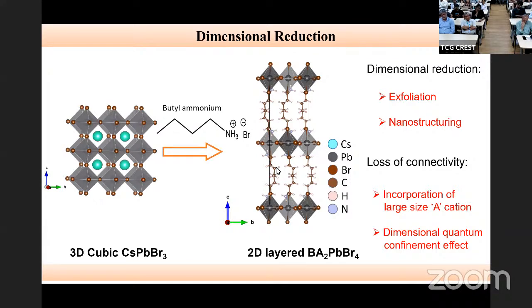Because now I told you that in this position, we can only fit in most of the time only two organic molecules, MA and FA. But once I've cut open like this, as long as the interaction at this end and that end are sufficient to cut open, what I do in the middle is up to me. And so I can make all kinds of organic molecules to accommodate them in there and change its properties by choosing the organic molecule. For example, I can put a hydrophobic material there, hydrophobic, so it will repel the moisture. Moisture will not come near it, and so I may be able to make it extremely stable.